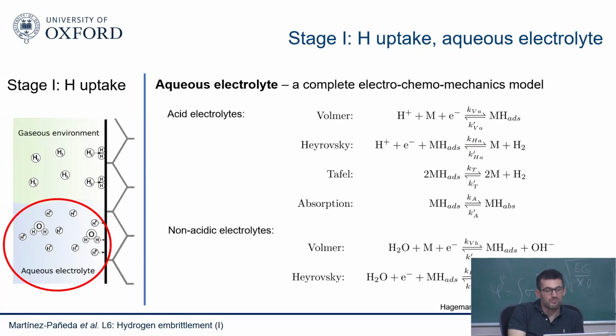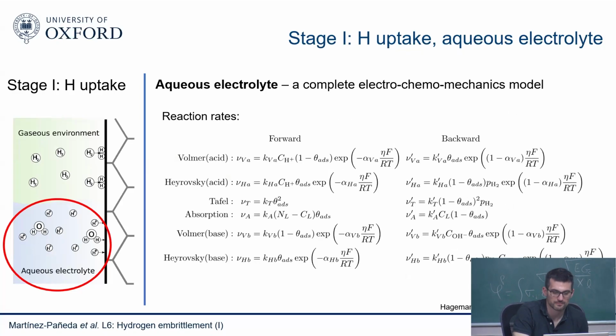The other thing is that they're very surface dependent. You may obtain material properties that relate to a smooth, polished surface, but in an engineering application that will change. So that's an issue. But basically the reaction rates look like this. I didn't put them up yesterday, but the key point to emphasize is not for you to learn all this math. If you look, for example, at the Volmer reaction here, what is it dependent on? The pH, this is the pH.